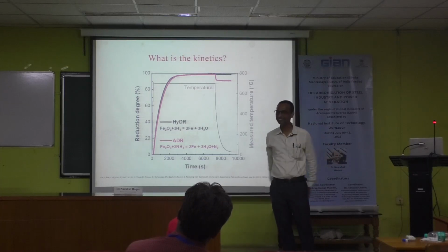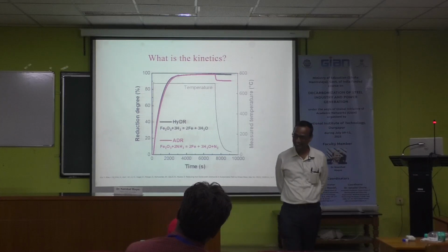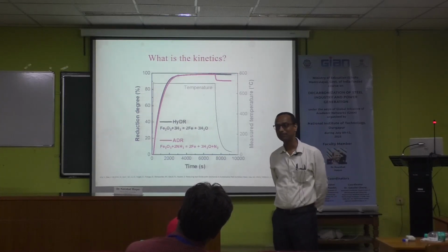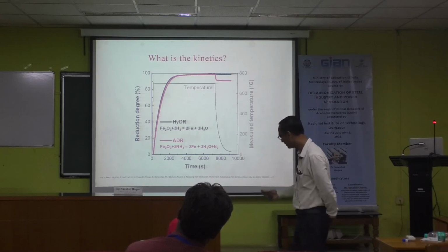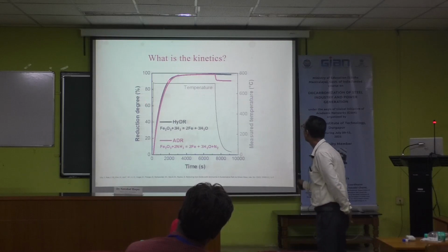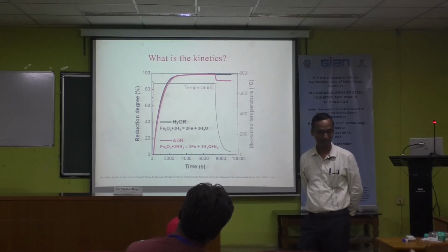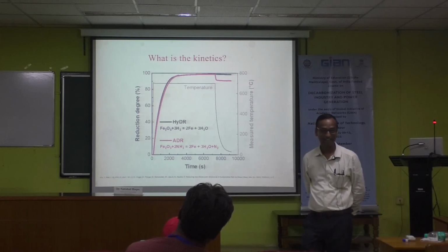Is this reduction percentage decreased? No, sir, it is a reversal. As we are measuring the reduction percentage from the weight loss, it means weight loss is going on continuously and suddenly weight gain is going on. NH3 is found again after the reaction. Nitrogen enters.